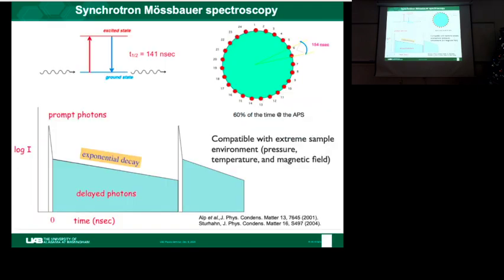Okay, I think many of you know this technique is actually achieved in the lab using a radioactive source. For example, for the iron 57 isotope, you use cobalt 57, and just using that decay radiation, you excite your iron 57 nucleus to the excited state, and you look at what's going on after the interaction. So at the synchrotron beamline, you can actually get rid of the dirty radioactive parent source and just tune your X-ray energy at that nuclear resonant energy and take data in the time domain and look at the decaying behavior in the different types of electronic conditions.